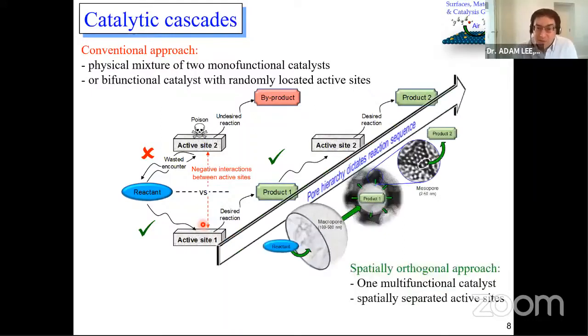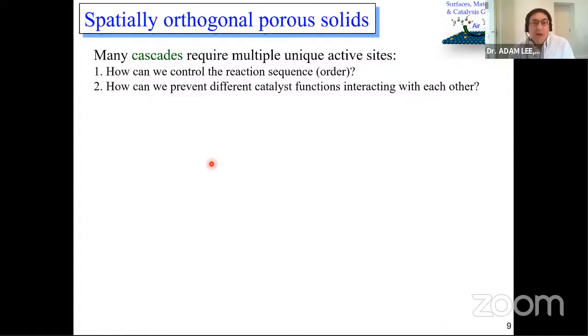And our solution has been to turn to porous materials, specifically hierarchically porous materials, where we can take a macropore, that can be a well-defined macropore, which we can functionalize with one active site, such that the reactant undergoes a transformation in this first area here to make product 1. And that product can then diffuse into much smaller mesopores, which you can see here. So product 1 goes into mesopores where there's a different active site, and it can then make a second product. So in this approach, we're using the pore hierarchy, the fact we have active sites spatially separated, as you can see here, to control the reaction sequence. So the goal, what we're trying to achieve, is controlling the reaction sequence and preventing different catalyst functions from interacting with each other.